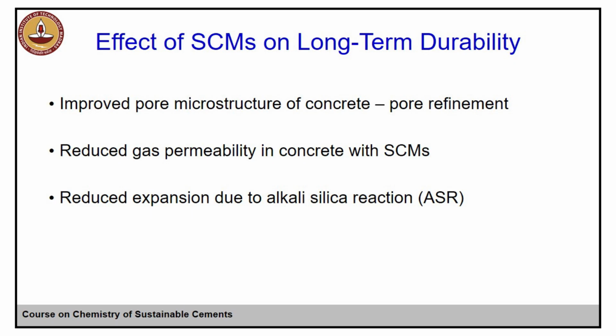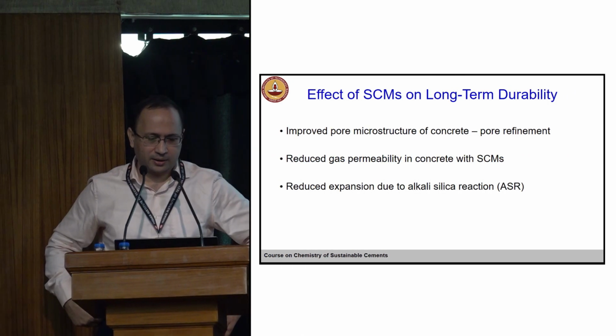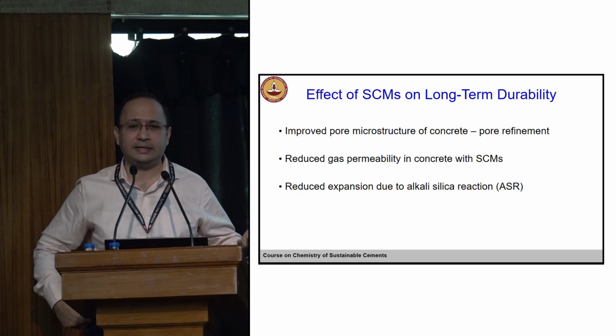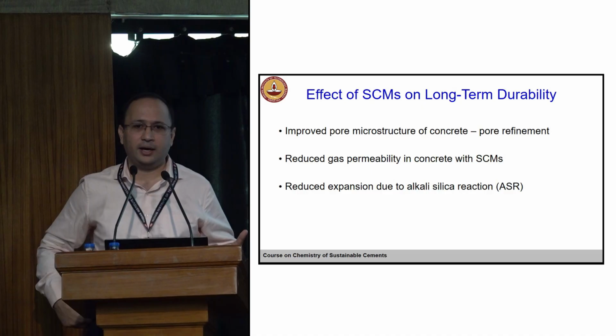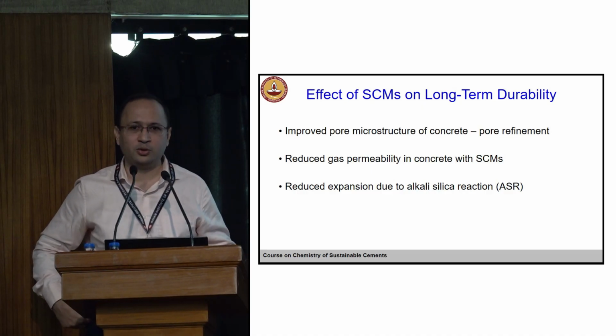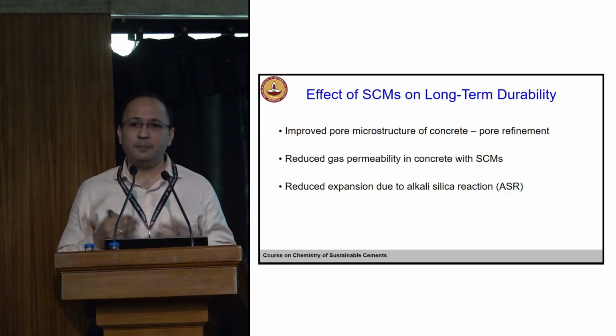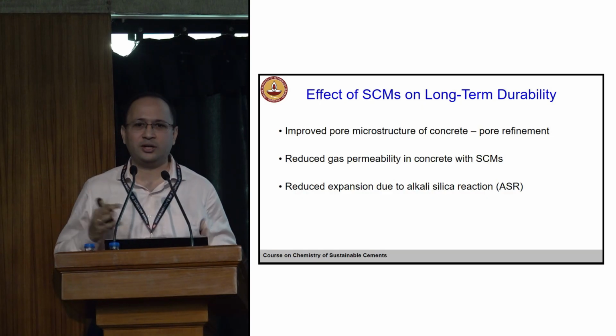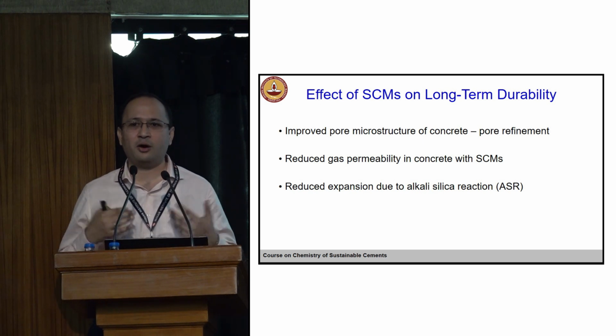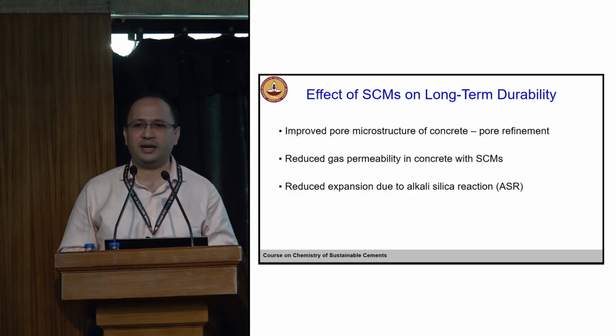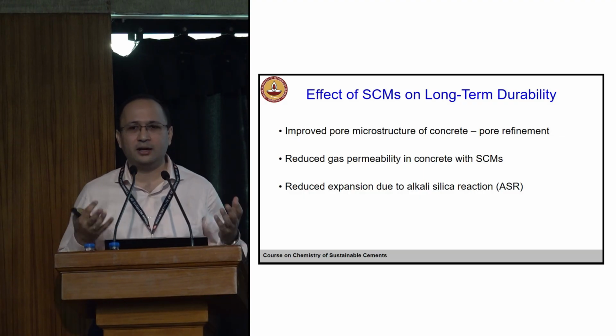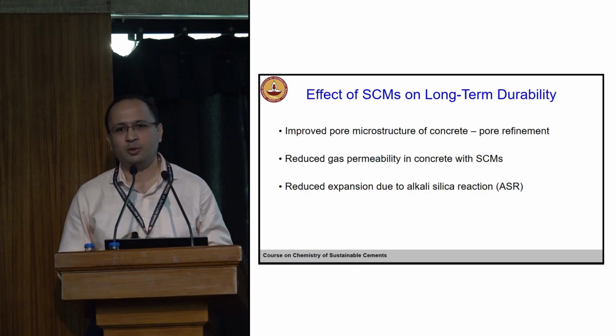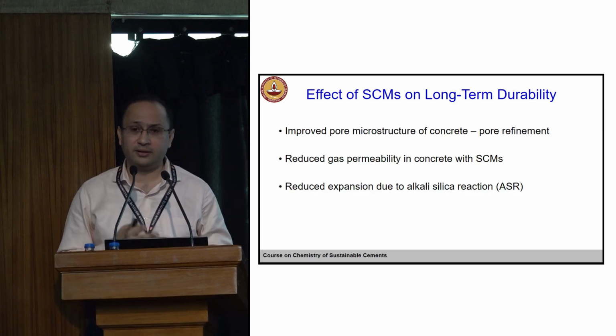So SCMs basically improve the microstructure of concrete by refining the pore structure, and they alter the CSH structure, its binding characteristics. That way it reduces the pH of the pore solution, which has implications on ASR. And depending on the type of SCMs you use, let's say limestone in combination with SCM, you may have a synergistic effect where you have stabilization of ettringite, the AFt phase, and formation of some additional phases like hemicarboaluminate or monocarboaluminate. So each SCM will behave differently, but these are some of the major things we need to keep in mind when we look at the SCM.